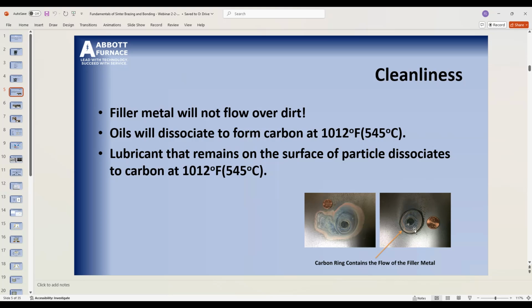The grease is a hydrocarbon. The hydrogen floated away because we got too hot, and it left the carbon ring. Now that carbon is dirt on the surface, and it won't allow that filler metal to go across. So we have to be sure that we get all the lubricant out, especially in that area where the joint is. And here's the thing.